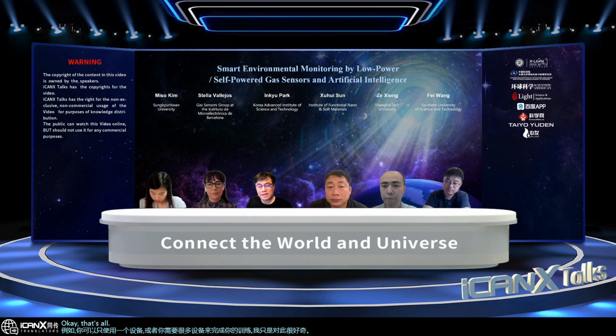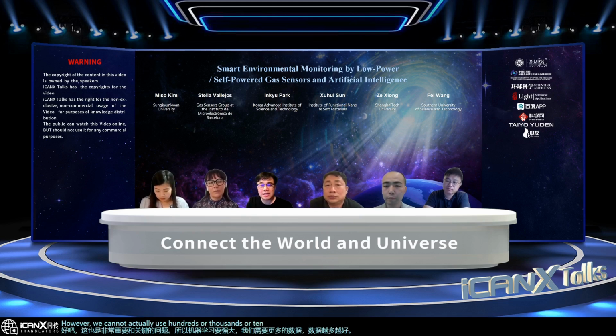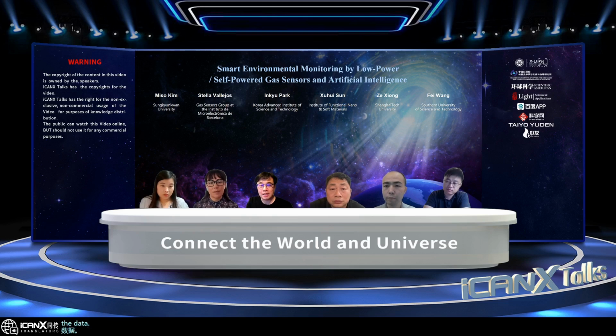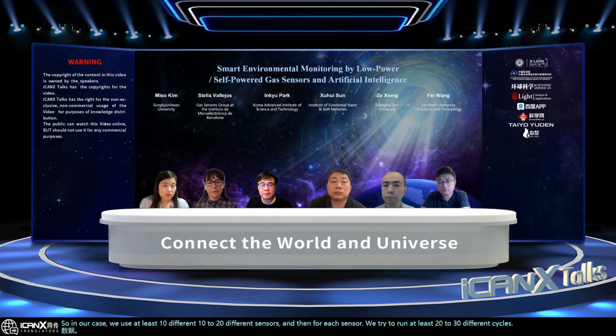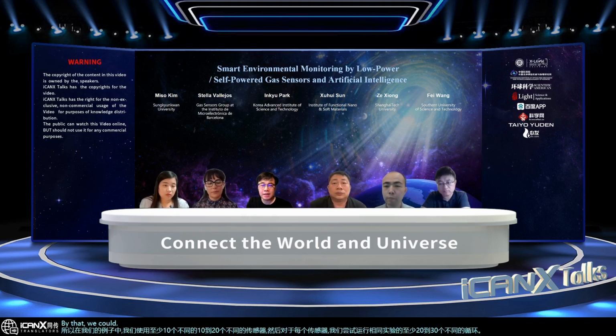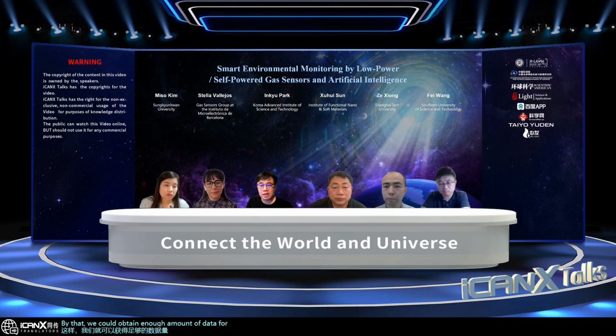Okay, that's also quite an important and critical question. For machine learning to be powerful, we need more data. The more data, the better. However, we cannot actually use hundreds or thousands or 10,000 sensors, especially for gas sensors, because the instrumentation of a gas sensing experiment is quite bulky, and it also takes a long time to obtain the data. So in our case, we use at least 10 to 20 different sensors, and for each sensor, we run at least 20 to 30 different cycles of the same experiment. By that, we could obtain enough data for the machine learning.